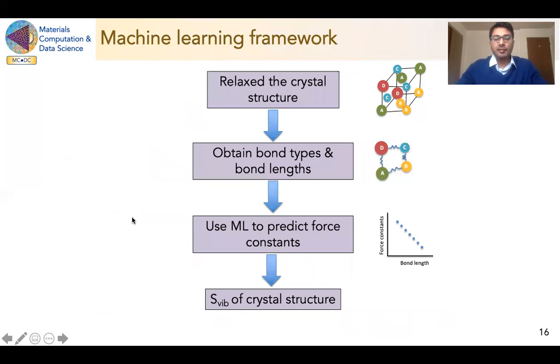So with this framework, which is based on machine learning, no extra calculations are required for the vibration entropy. Only one calculation is required for the electronic relaxation of the model alloy, which is needed anyway for the calculation of enthalpy of mixing. So first, we relax the structure, and after relaxing the structure, bond types and bond lengths are obtained, and then machine learning is used to predict the force constants, which ultimately gives the vibration entropy of the alloy.